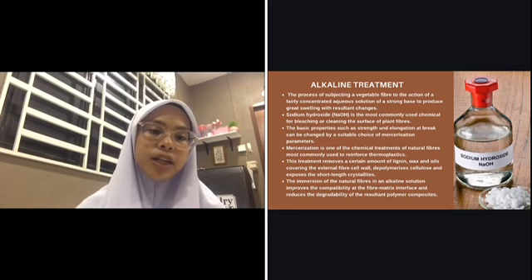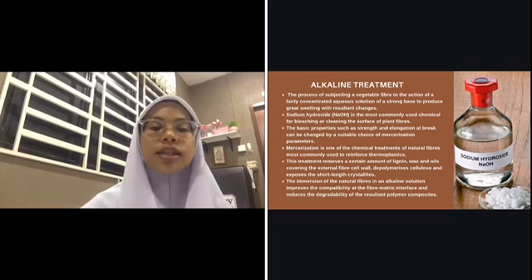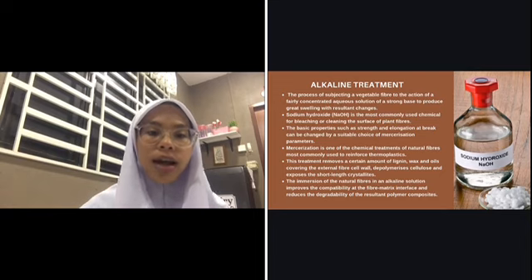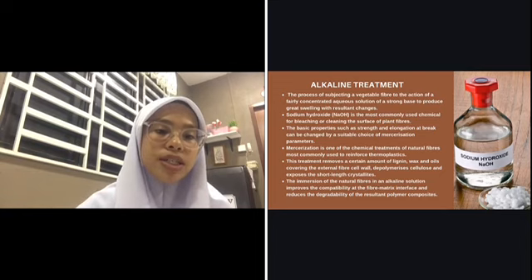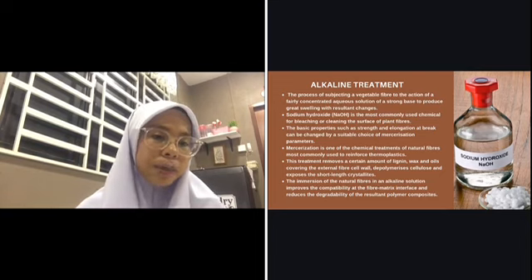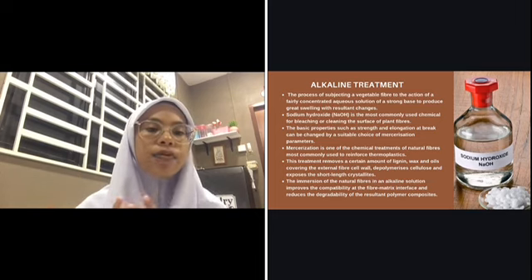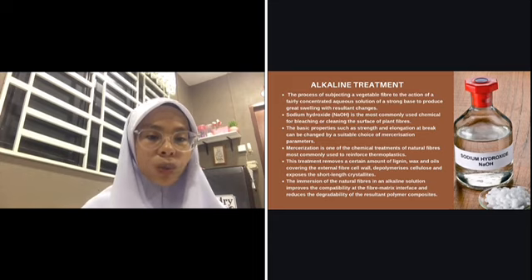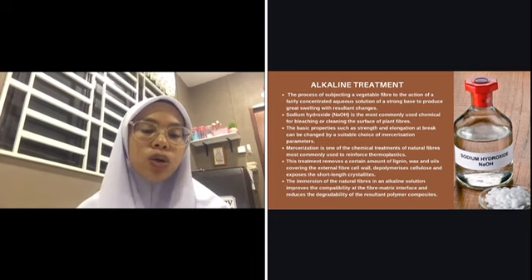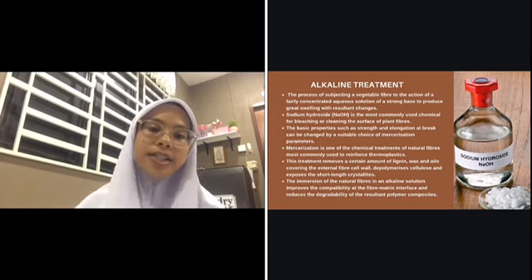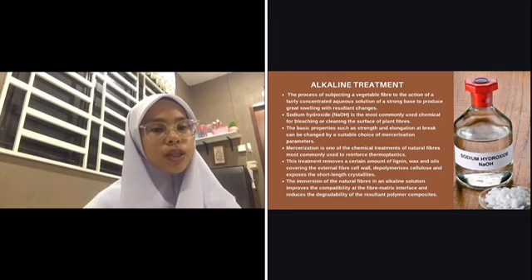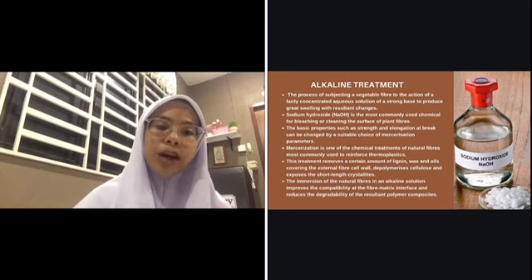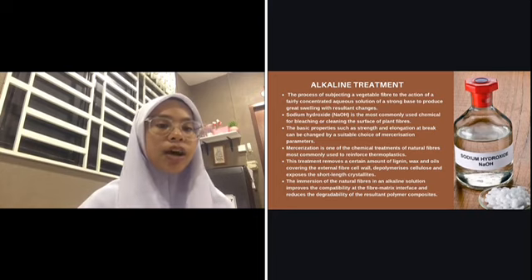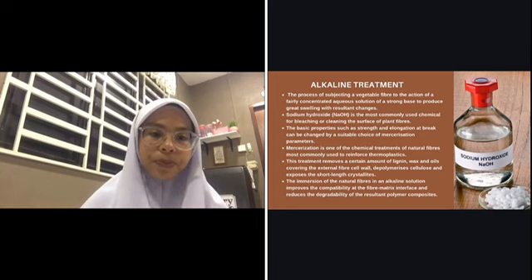The important modification resulting from alkaline treatment is the disruption of hydrogen bonding in the network structure, thereby increasing surface roughness. So this treatment removes a certain amount of lignin, wax, and oils covering the external surface of the fiber cell wall, depolymerizes cellulose, and exposes the short-length crystallite. So the addition of aqueous sodium hydroxide to natural fiber promotes the ionization of the hydroxyl group to the alkoxide.